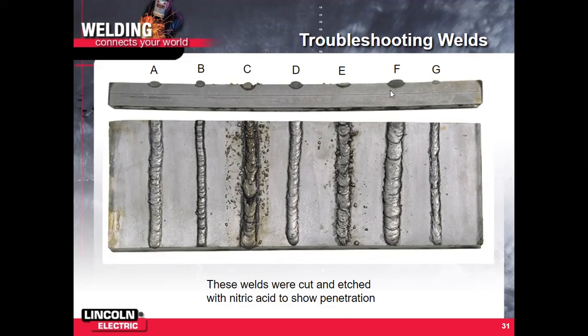It shows you the profile here. We got good penetration, decent bead profile. Here, we got a rod that's hitting quite shallow. We see it does not penetrate in the plate very much, but it's fairly wide. There's lots of spatter here too. So that's maybe not a desirable weld profile. I'd like you to produce some nicer stuff than that. Here, D, I think D is one of the nicer ones here. Got a good looking weld profile. It's kind of a combination of the C's and B's. Moved a little quick in some spots, but if we look at here, we got good penetration to the plate.